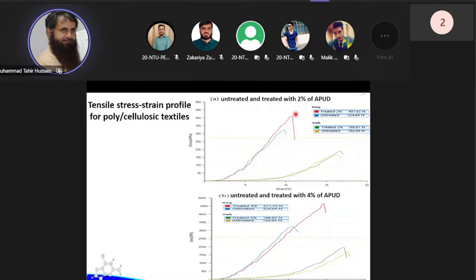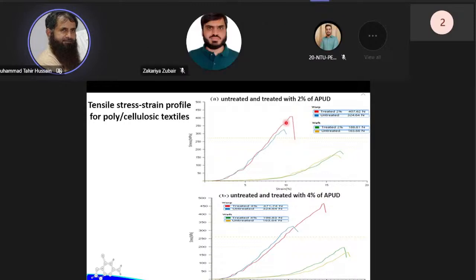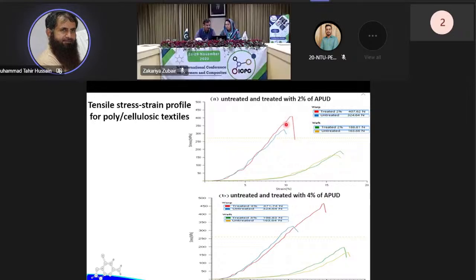So the tensile strength along the warp is increased using the aqueous polyurethane dispersions, and similarly along the weft, the same effect was observed. The aqueous polyurethane finish has increased the tensile behavior of our materials. And similarly, with the 4%, the same effect was observed: by using the aqueous polyurethane finish, the tensile strength of our material was increased along both the warp and weft sides.